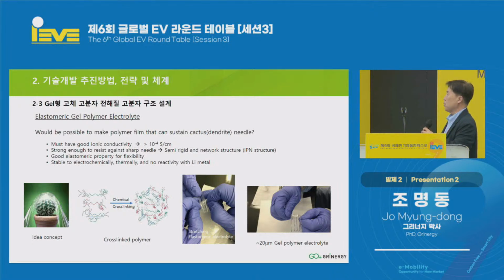and this has a great ionic conductivity. It's strong enough to resist a sharp needle. And it's a semi-rigid network structure. It's great. It can come up with an IPN structure. And that was the idea that we came up with. So, once again, electrochemical and thermal stability and non-reactivity were what we really cared about.